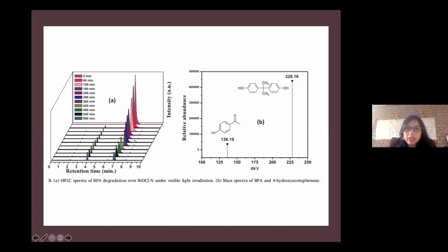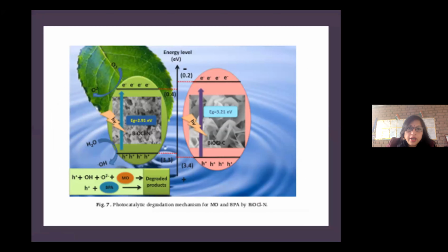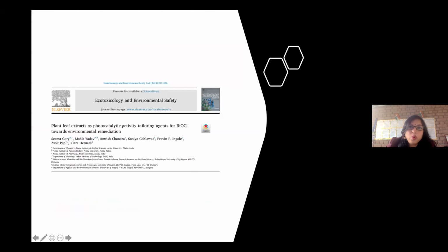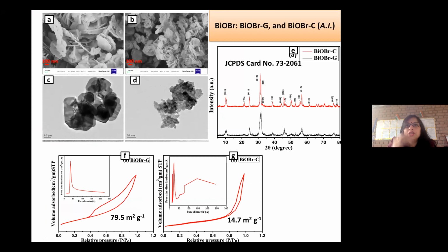So these are the results of BiOCl, and the mechanism was given that this is the band gap of 3.21 electron volt, but when this was prepared by the green route, the band gap was reduced to 2.91 electron volt. And because of the leaves, the surface area was enhanced. And moreover, this shows enhanced photocatalytic activity because of the separation of electron and hole pairs. So this paper was published in Ecotoxicology and Environmental Safety journal, Elsevier.